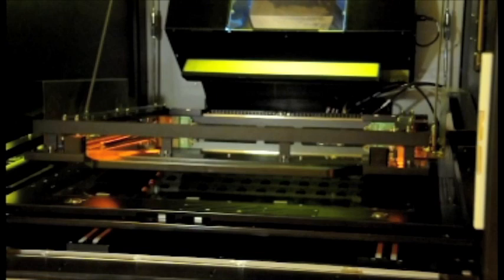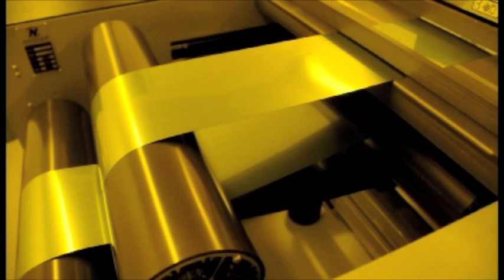In the printing process, the resist coated metal and tooling finally come together. Simply put, printing is the selective exposure to UV light of the photoresist on the metal. Tooling, the top and bottom films for double-sided exposure, are first loaded into the vacuum frame. Unexposed metal is paid off an unwind unit.